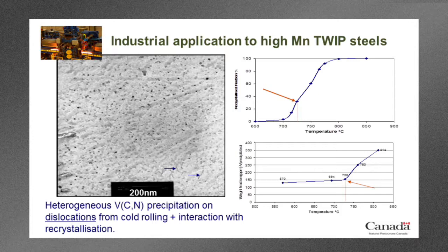These are precipitates that formed on a dislocation, and that dislocation had to come from the cold rolling, so that suggests very strongly that these precipitates formed before recrystallization, during the heating stage after cold rolling. Here what we can see is the recrystallization kinetics curve. So we measured the recrystallized fraction as a function of temperature.